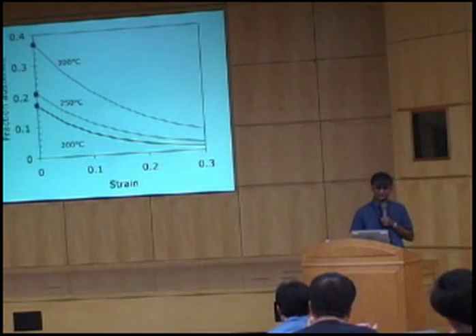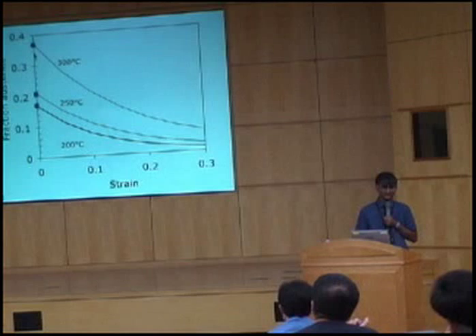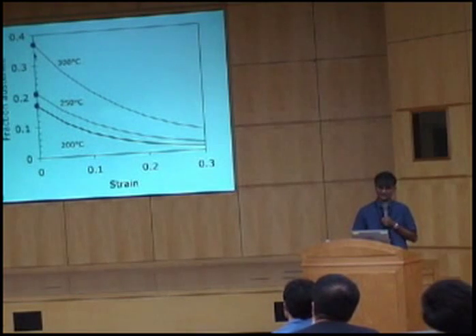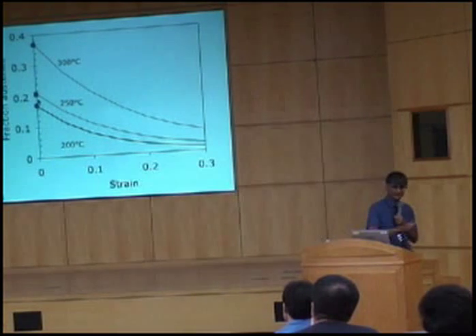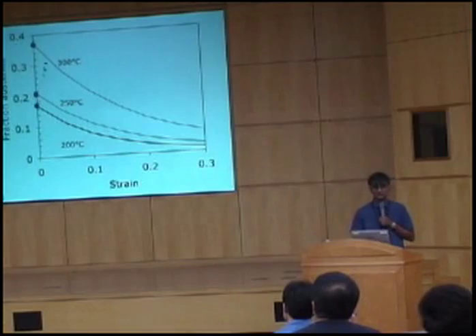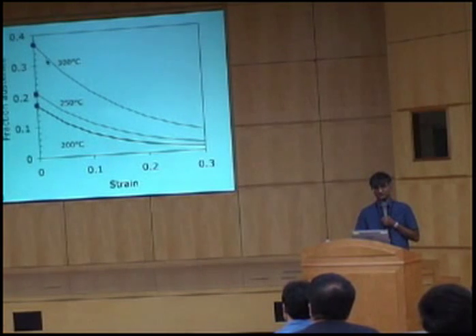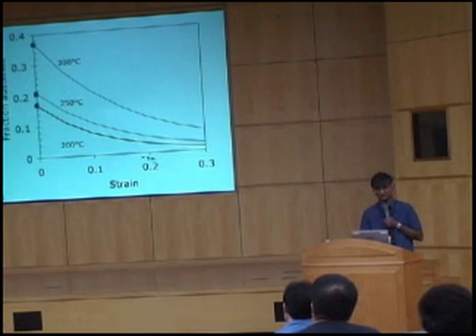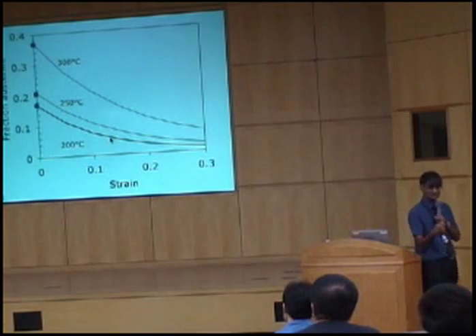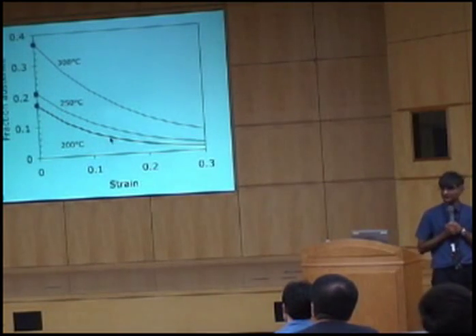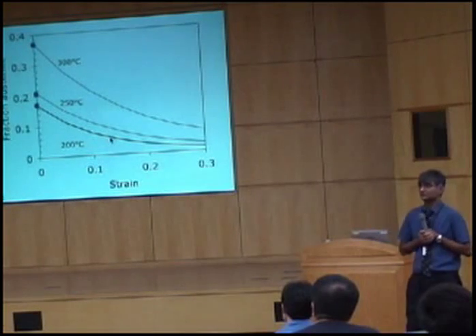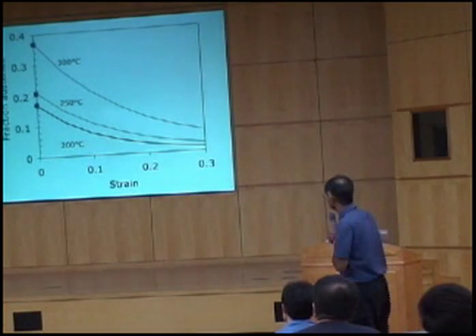So let's take three steels, all of them with the same microstructure of bainitic ferrite and austenite. And starting austenite contents are given by these blue dots. As I pull them, the austenite will start to decompose to martensite in this way. These are calculated curves. Okay? So I expect the austenite to transform into martensite as I pull them by stress or strain-induced transformation.